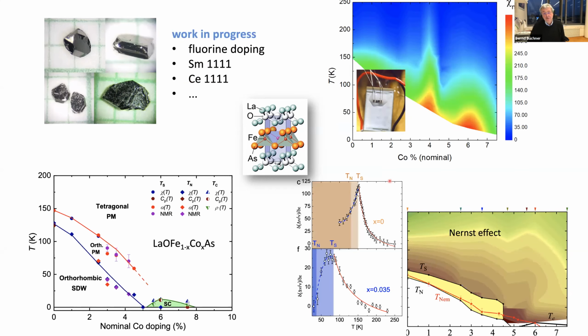And then at the end, I've shown you some first results on strain derivatives of more complex transport properties like the Seebeck effect and Nernst effect. All of them strongly depend on the lattice, which very strongly shows that the nematic instability is crucial for the electronic state here. And I think that also gives us, let's say, first new approaches to understand this coupling, which seems to be band selective, and which seems to be very strongly connected to the Fermi surface.